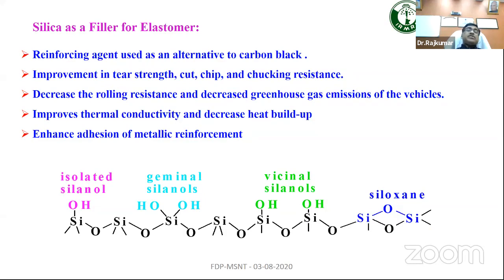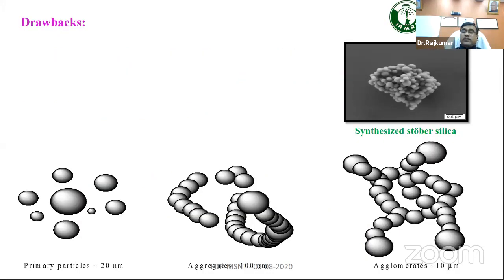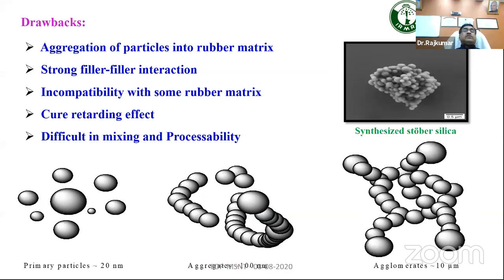Of course, the surface treatment of silica plays a very major role in doing that. The drawback is the aggregation of particles in the rubber matrix, as I was telling, with strong filler-filler interaction, incompatibility with the rubber matrix, and cure retardance effect. Especially because these fillers are acidic in nature, whereas the curatives are usually basic, the curatives start reacting with this material and hence retardancy takes place. That means the curing will not take place on time, so you may have to give more time. Mixing and processability are also difficult with low particle size, rather nanoparticles. So these are some of the drawbacks of these materials.